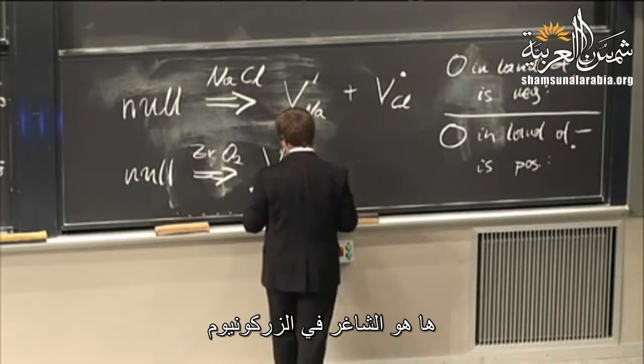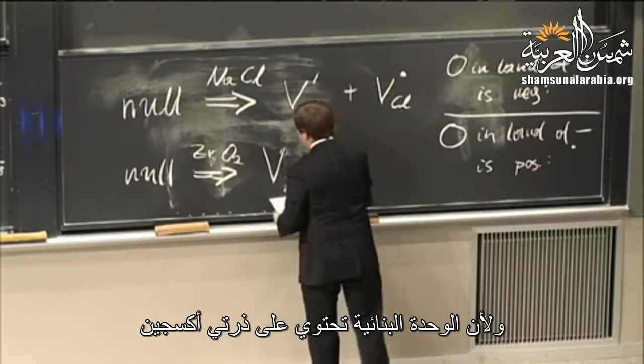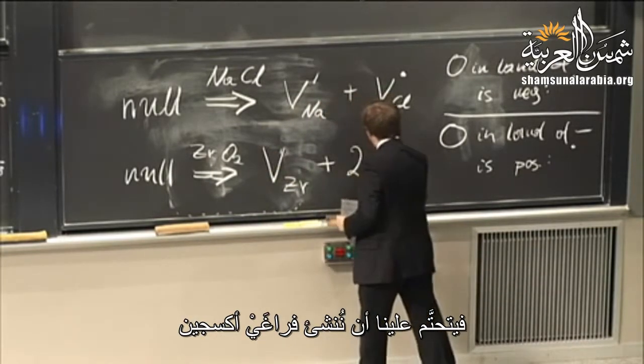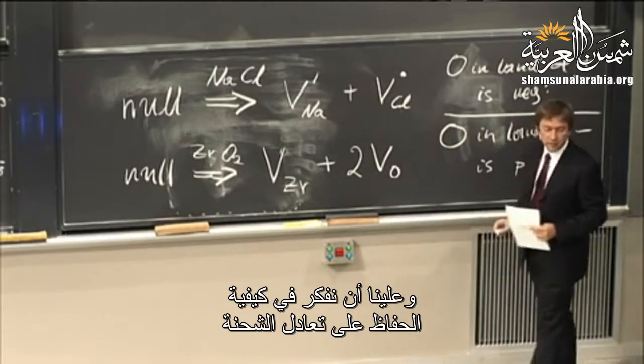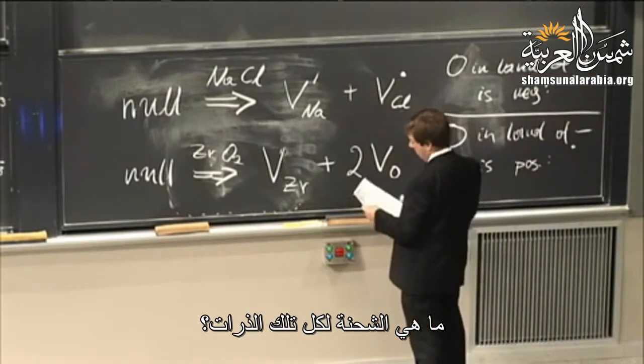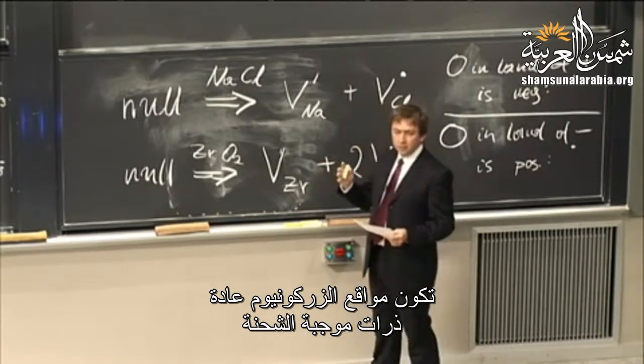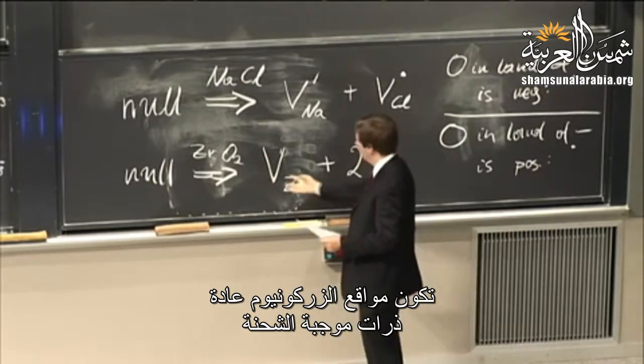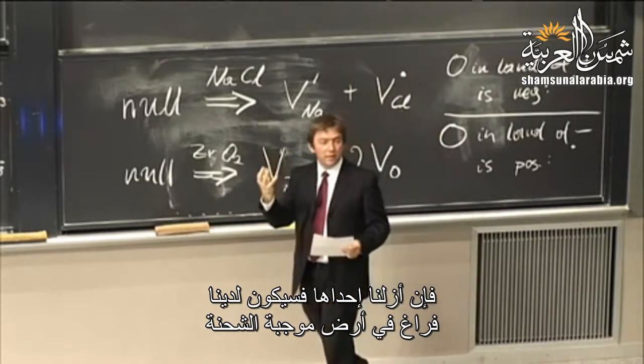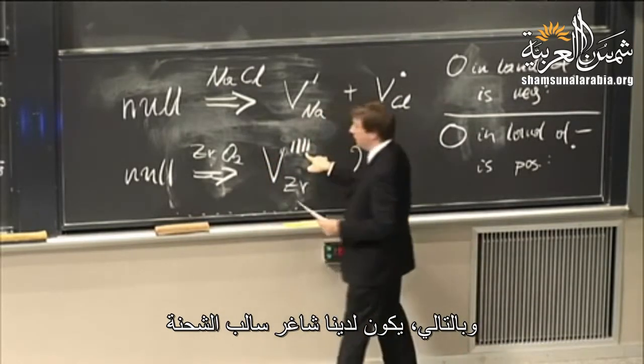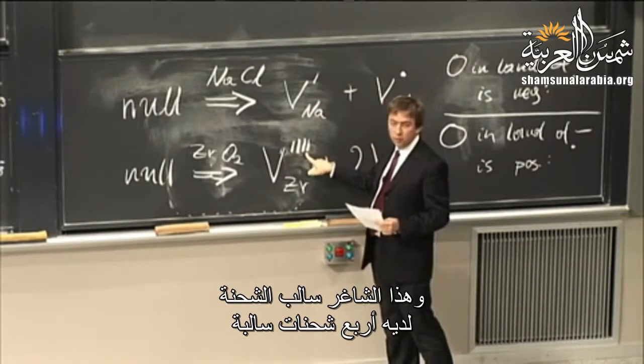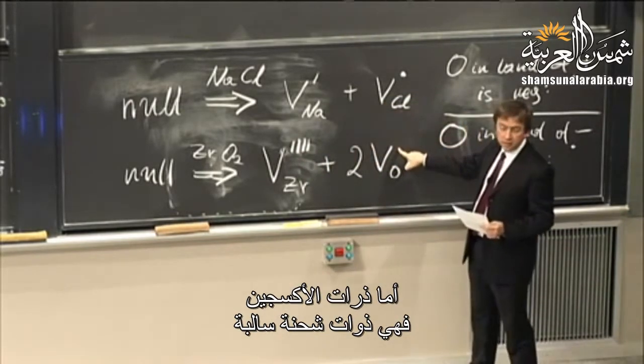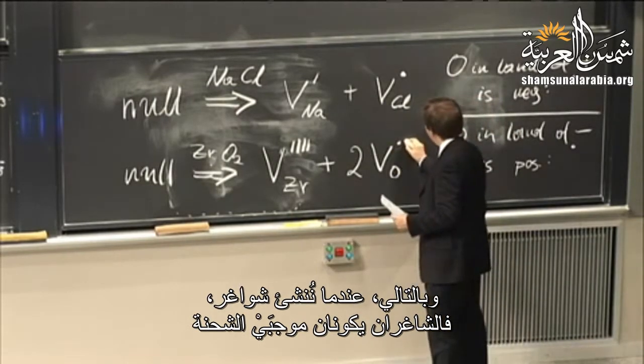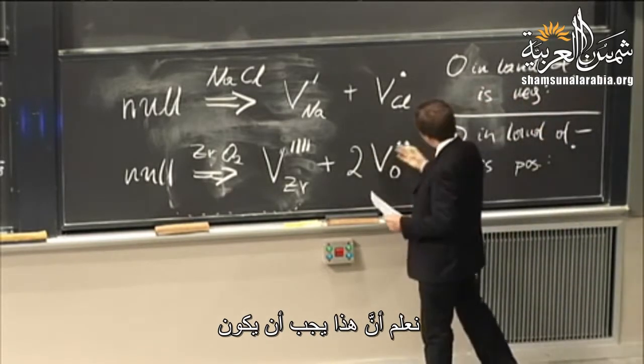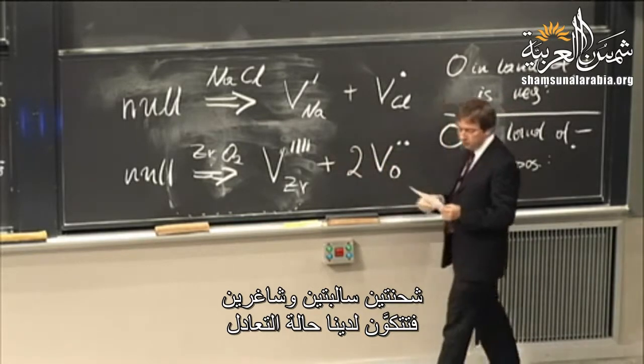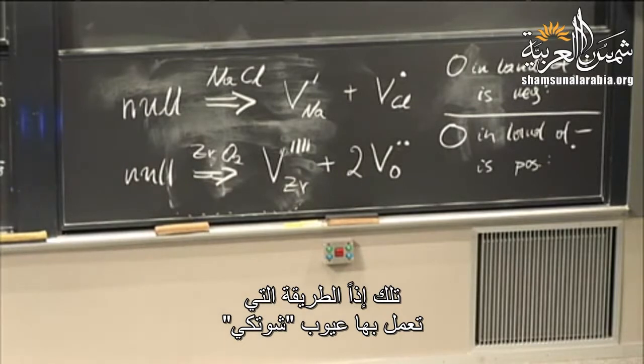We have to create vacancies. Here's our vacancy on the zirconium. And because this structural unit contains two oxygens, we have to create two oxygen vacancies, right? And now we have to think about how we maintain charge neutrality. What is the effective charge on all of these atoms? The zirconium sites are usually the positively charged atoms, right? So when we remove one of them, that's putting void into a land of plus. So we have now a negatively charged vacancy, and this negatively charged vacancy has an effective charge of negative 4. And the oxygens are the negatively charged ions, and so when we create voids there, these two vacancies have an effective positive charge, and because the charges have to balance, we know that this has to be effectively 2 negative charges, and there are 2 vacancies, so we have charge neutrality. So that's how the Schottky defects work.